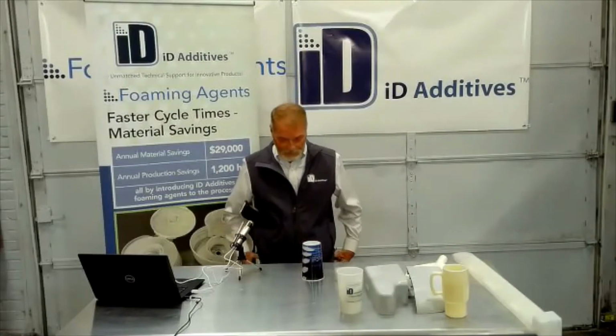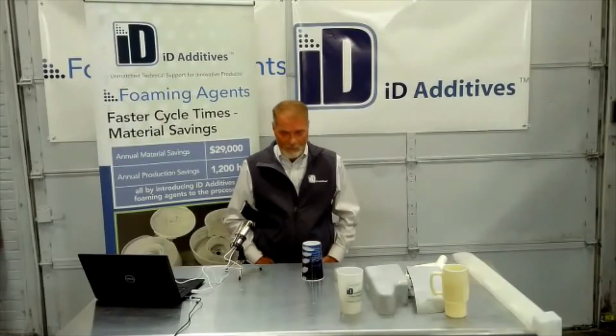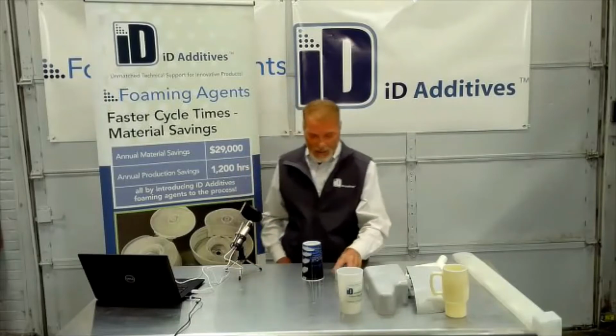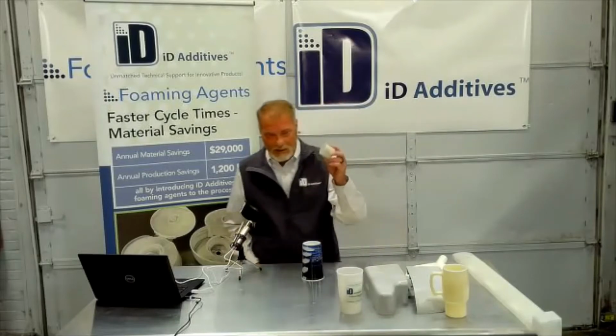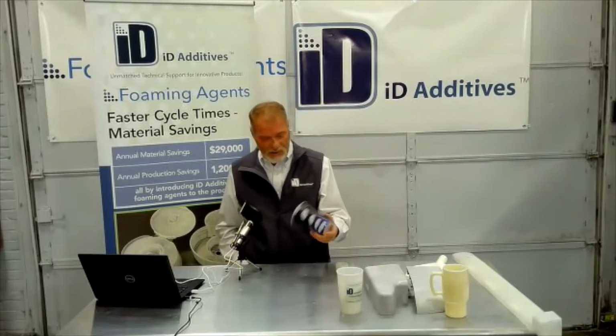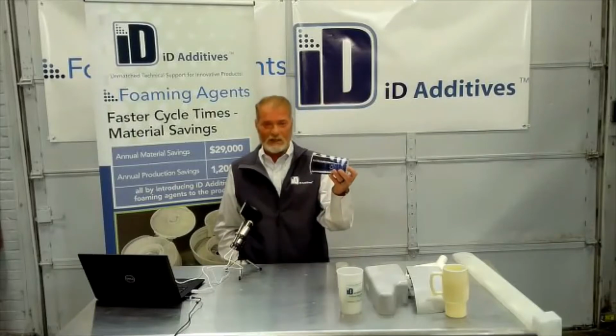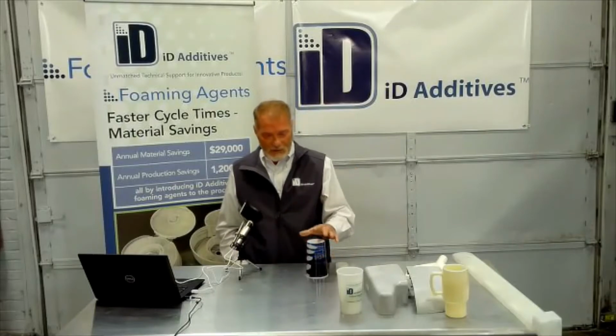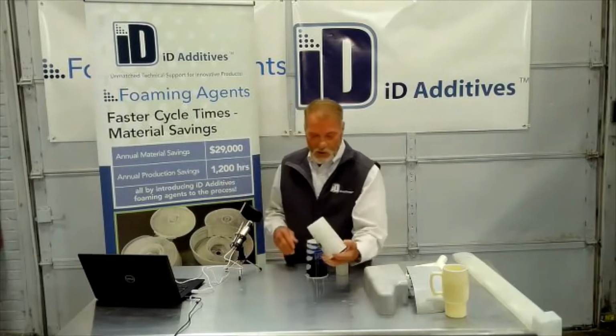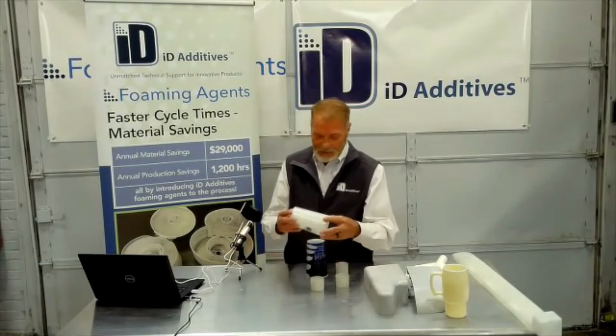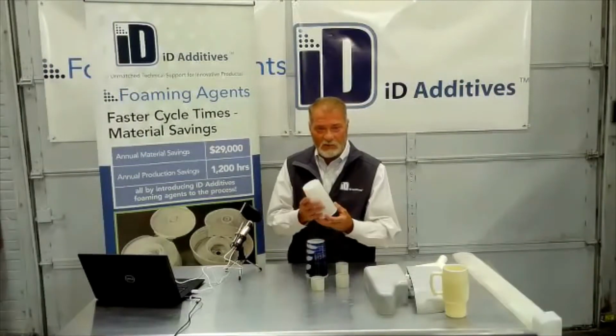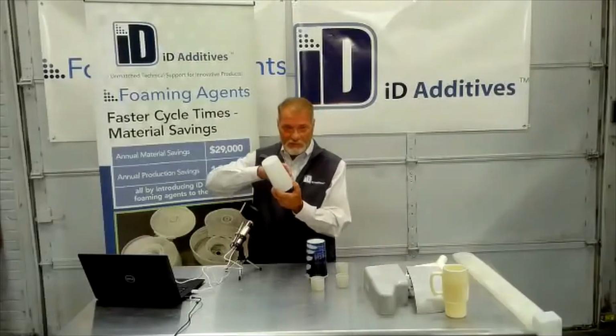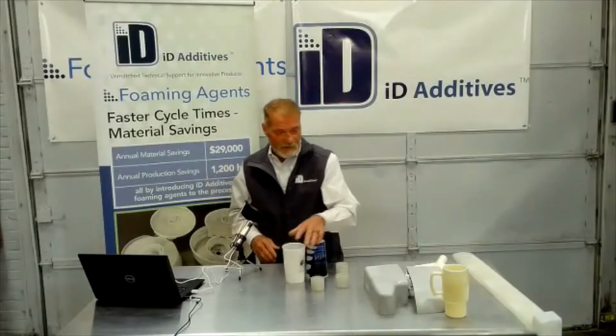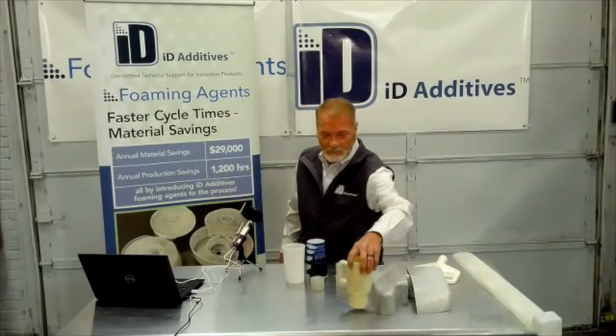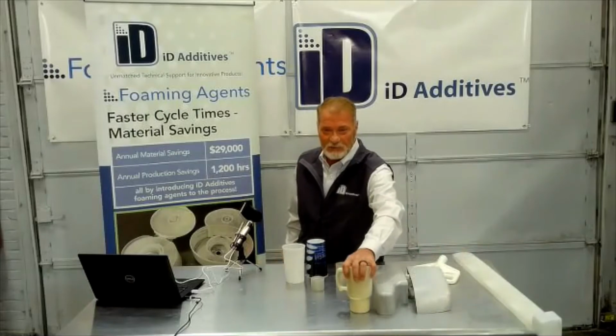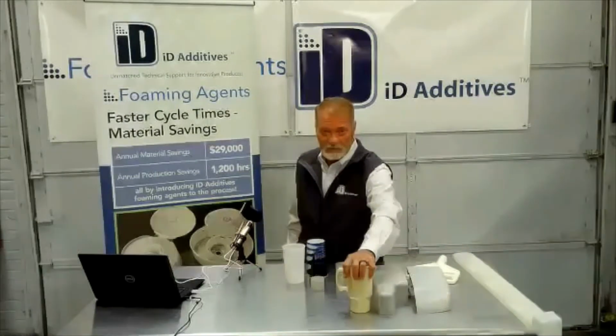And so I really want to focus. I've done caps. This was injected at like 0.2 seconds. These were injected at like 0.4 seconds, 0.3 seconds. Highly aesthetic, no foam on the surface. Everything's just a beautiful gloss surface. Cell structure from here all the way up. This is PLA, a very heavy material, and we took 30% of the weight out of it.